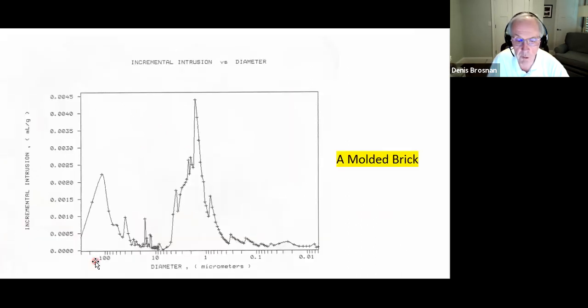So here's a mercury porosimetry test result. This is a molded brick. And this is expressed as incremental intrusion versus diameter. So diameter on the bottom axis, we've got 100 microns, 10 microns, 1 micron and below. And this is the volume of intruded mercury.